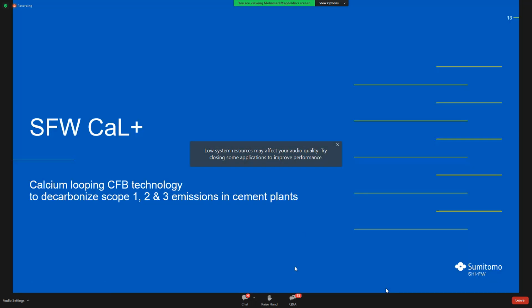The flue gas comes into contact with the first unit, which captures the CO2 to form calcium carbonate via the reaction shown. The calcium carbonate is then directed to a calciner, which operates as an oxy-fuel calciner to produce concentrated CO2 and recirculate back the calcium oxide, hence the looping aspect in the system. So this is a closed loop where calcium is used to capture and release the CO2.